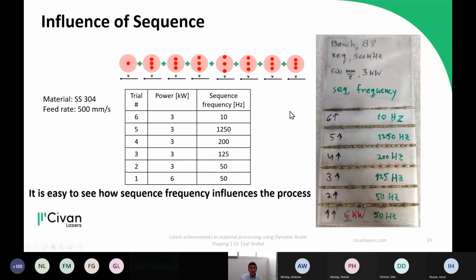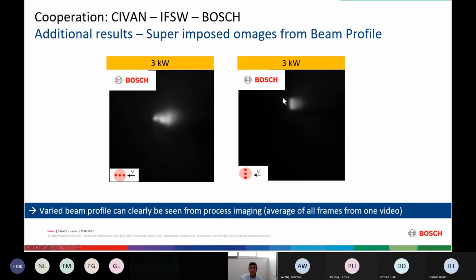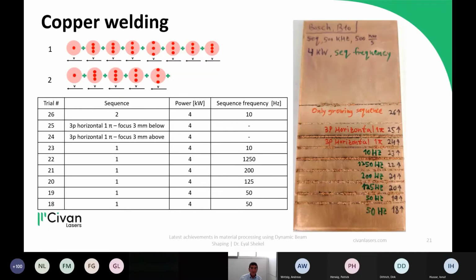Now, this was really done in preparation for copper. Everything we do, we take pictures with a fast camera. So this is a nice trick that was done here by Bosch. They overlaid all the frames from the fast camera, and you can actually see the 3 points. We did both this direction and this direction. You can see it in the video, which is low resolution, but when you integrate over many frames, you can actually see the beam shape on the material itself. So anyway, this was really done for copper to see how we can optimize copper welding.